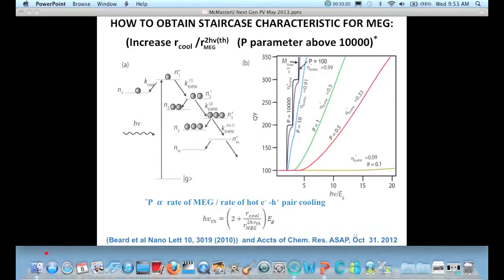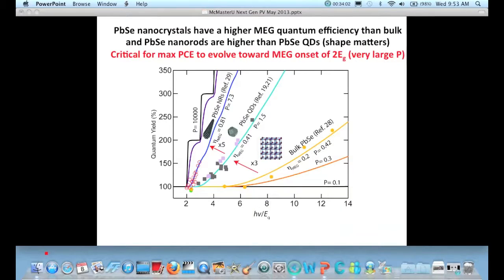Now, as I said, we need the step function to get the highest efficiency. And currently, this is bulk material, which is way down here. And experiments are slowly moving toward the step function. To get the step function, it was shown in this paper that you need to have the ratio of the cooling rate to the MEG rate to be about 1 over 10,000. And that'll give you the staircase step function. Currently, we're about 10, so we're getting close, but not quite there, to get the step-like function.